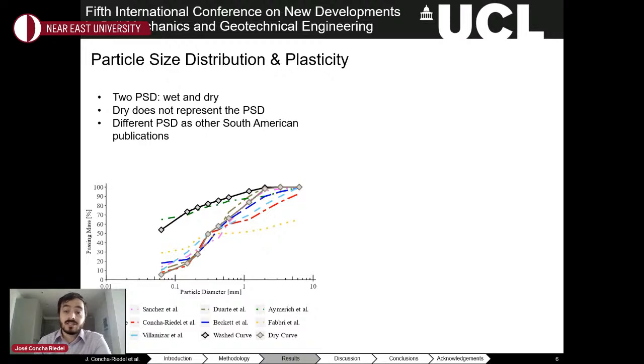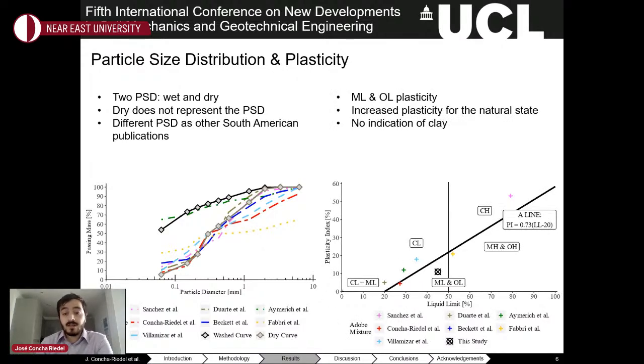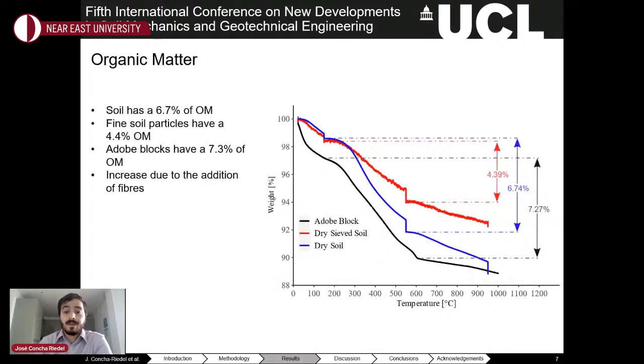If compared to other South American researches on earthen materials, then the soil seems quite different, with a higher number of fines. For the plasticity, the soil fell into the category of a low plasticity silt or an organic soil. There was no indication of clay from the plasticity chart, as the soil is below the A line. Two other tests were conducted for plasticity using oven dry and washed soil. Both of these tests resulted in lower plasticities.